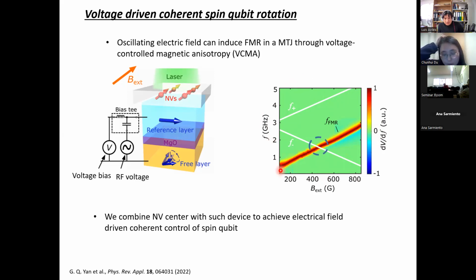Oh, okay. Yes, so the F plus and F minus. This is not an NV measurement. We apply a radio frequency voltage to induce the precession of the free layer, and we measure using the spin torque FMR geometry: we send the voltage and induce the FMR, and this generates a mixed voltage that we can measure. So we monitor this STFMR signal as a function of magnetic field and frequency, so we can get the resonance condition of the free layer of this MTJ.